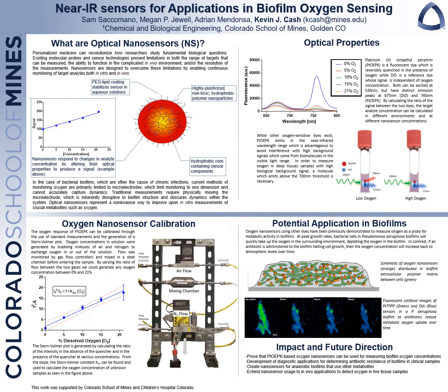While there are a variety of dyes that are sensitive to oxygen as well, we use a dye called platinum octaethyl porphyrin ketone, or PtOEPK, because of its unique spectral properties to emit in the near-infrared wavelength range. This is an important characteristic of the nanosensor because in many biological samples, background signal can be very high at visible wavelengths.